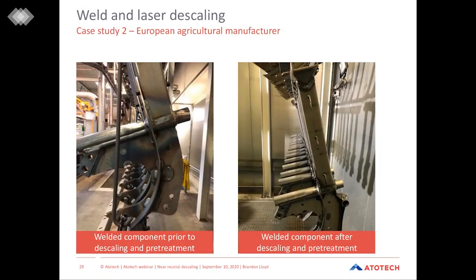Another improvement that they were able to achieve was significant reduction in the burn areas, which did present some issues to them in the past. The image on the left is a welded component prior to descaling and pretreatment. Along the welded areas right in here, we see a significant amount of the heat affected zones from the welding applications. If we look at the image on the right, what you'll want to look at is along the bottom area here. This is the welded component after descaling and pretreatment. You can see almost complete removal of the burn areas and heat affected zones, which again presented a significant issue for them in the past with their other proprietary chemicals.